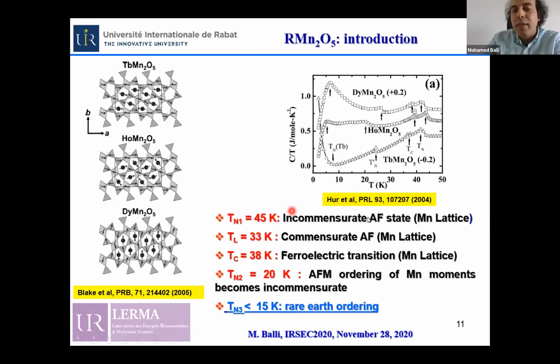On the other hand, this incommensurate antiferromagnetic state transforms into a commensurate antiferromagnetic state at 33 Kelvin, then again becomes incommensurate at a temperature of 20 Kelvin.